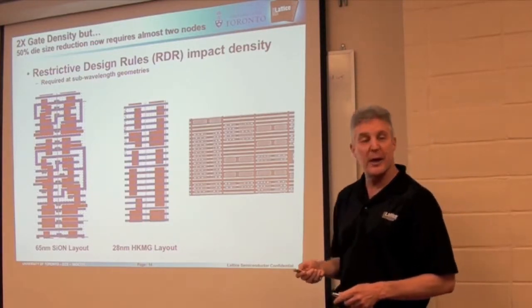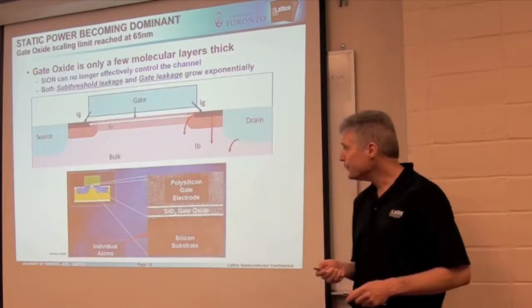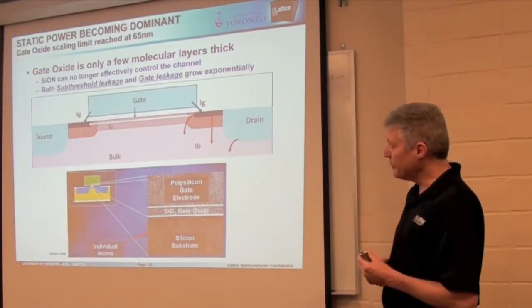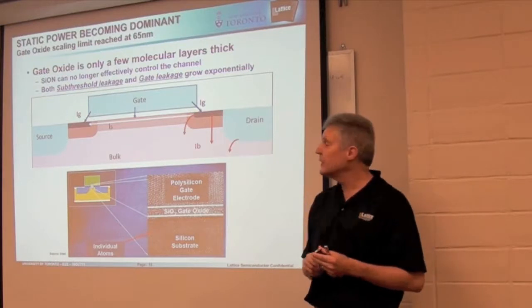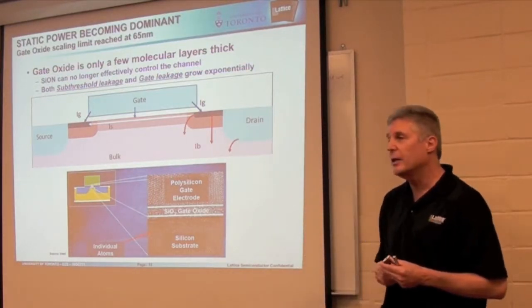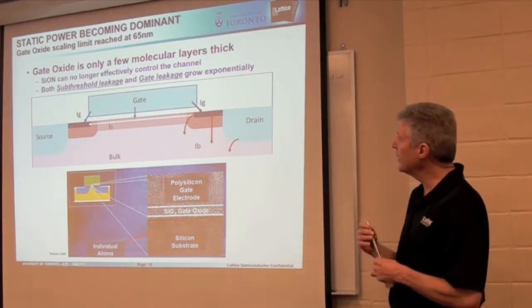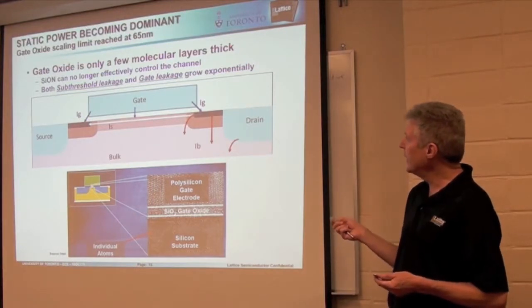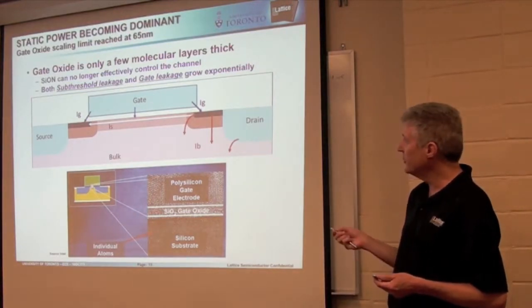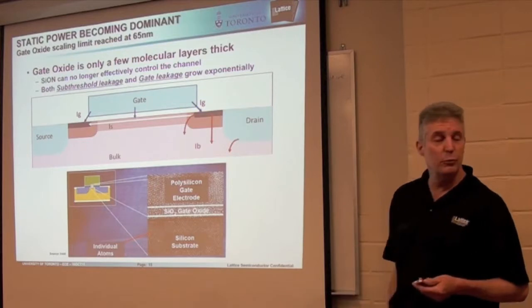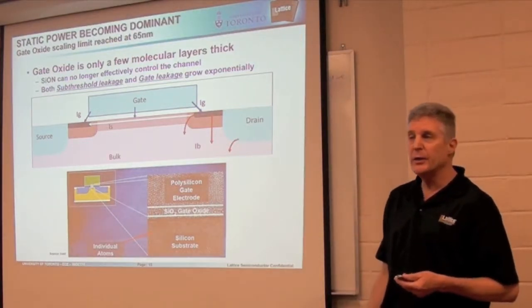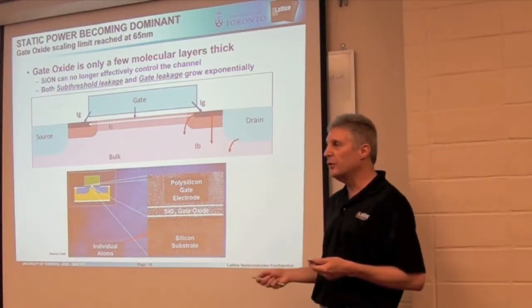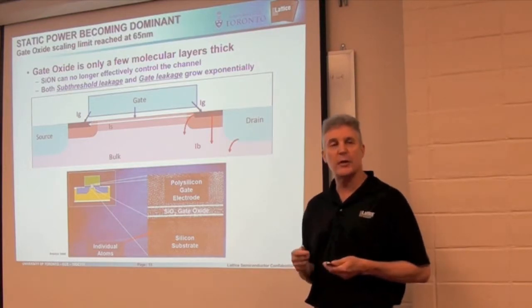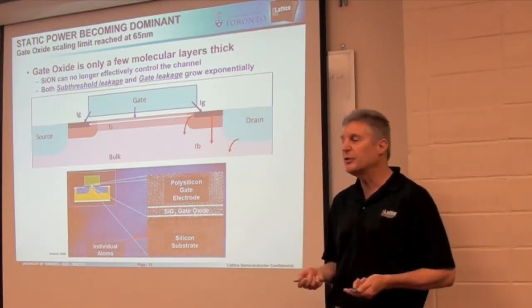It doesn't show up in your schematics, but it shows up in your layout. So let's talk about static power now. This is becoming dominant at 65 nanometers and beyond, and this is why we had to move to HighK metal gate. Basically, gate oxide on these devices at 65 nanometers is only a few molecular layers thick. And it's no longer acting as an insulator, it's actually becoming conductive.